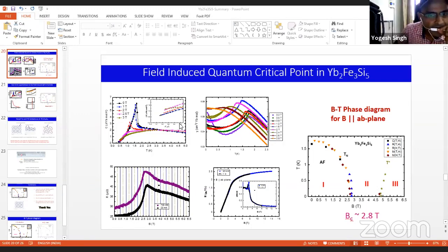Right. My understanding is that the Kondo effect starts to screen the local moments, and therefore the entropy of the local moments will go into the conduction electrons. If you look at, for example, ytterbium rhodium 2 silicon 2, where the local moments are almost completely suppressed, you can see a huge Fermi surface, much larger than what would have been there from only conduction electrons. So by hybridization, the local moment is going into the conduction electrons. That is the point.